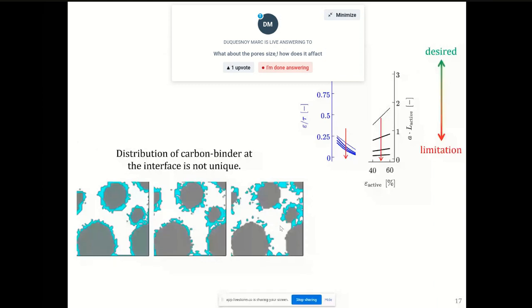Right. So your pore size will affect... as long as you have a unimodal distribution, right? As long as you have all spherical particles which are the same size, no matter whether those particles are 5 micron or 50 nanometers, your tortuosity value will be the same. And you can do the mathematics. The length scale just cancels out when you do the dimensional analysis.